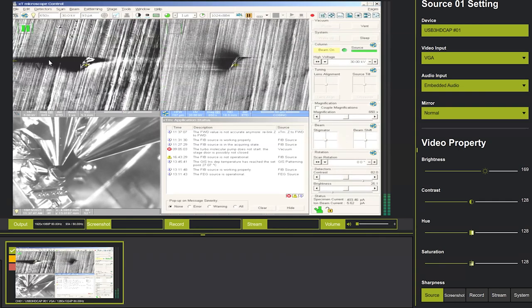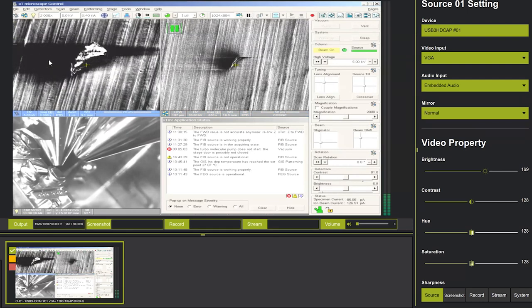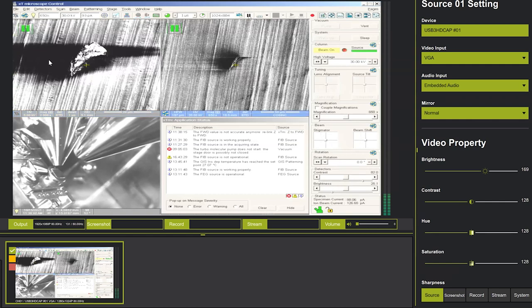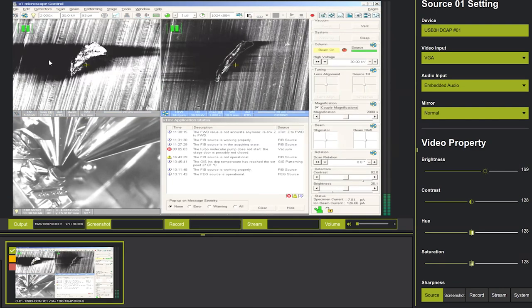Okay, let me pause it here. So I didn't move the stage. I just switched the imaging mode to the ion beam mode. Then the two beams are hitting about the same location. The electron beam image is from an angle, okay? Then the ion beam image. From top down, this particle sitting on the surface looks like this, but with the electron beam, it looks different because your view is not from the same angle, okay? But it's important to find the Z height where the two beams hit the same spot.